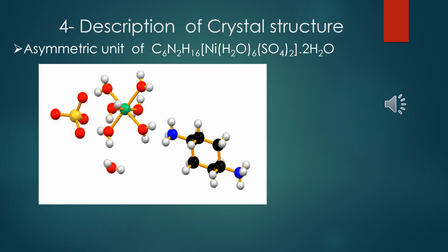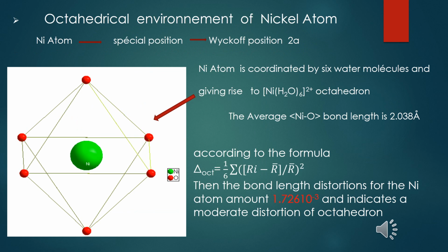The X-ray analysis revealed that the asymmetric unit of this compound is made of one trans-diaminocyclohexane molecule, one free water molecule, 6 coordinated water molecules, one nickel atom and one sulfate group. The nickel atom is located on a special position, the center of inversion, described by Wyckoff position 2a. This atom is coordinated by 6 water molecules and gives rise to the nickel hexaaqua octahedron.